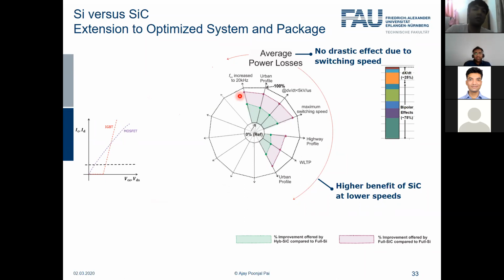Then let's look at what happens at higher temperatures. So far we were discussing the average power losses, right? Yes. So now we will change it a bit and discuss the total chip content, or the total semiconductor content, I would need in a module for a given mission profile or a given operating point. Now, if I dimension a silicon carbide module for 125 degrees Celsius max junction temperature, then the silicon carbide module could be half the size of an IGBT module. I mean, it could offer like 50 to 60% saving in the chip content, meaning that for an IGBT module, if you need something like 300 square millimeters, with the SiC module you might need 150 or maybe 120 square millimeters.